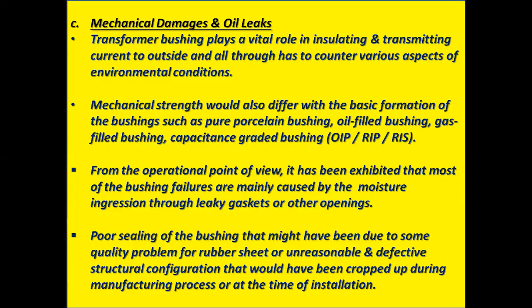From the operational point of view, it has been exhibited that most of the bushing failures are mainly caused by moisture ingression through leaky gaskets or other openings. Poor sealing of the bushing might be due to some quality problem or manufacturing problem for the rubber sheet, or unreasonable and defective structural configuration that would have cropped up during the manufacturing process or at the time of installation.